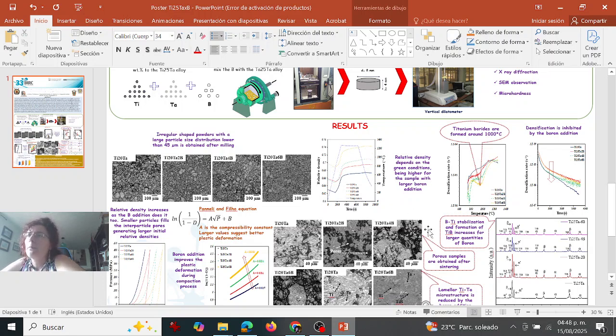All right. If we have a look at this graphic where we have the densification rate versus temperature, and we have a look at these curves, we observe that the titanium borides are formed around 1000 degrees. And in this graphic, where we have the densification rate versus time, we conclude that the densification is inhibited by the boron addition.